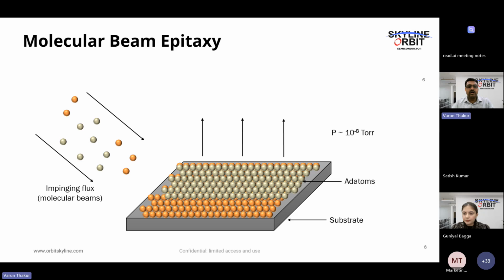now coming on to what is a molecular beam epitaxy method. So here we have an impinging flux of material which is called a molecular beam. Basically, we use material in its physical form. No chemical compound is used. The physical material is evaporated using temperature. So we use wires to pass current, which increases the temperature, and it evaporates the material onto a substrate which is typically kept at a higher temperature.